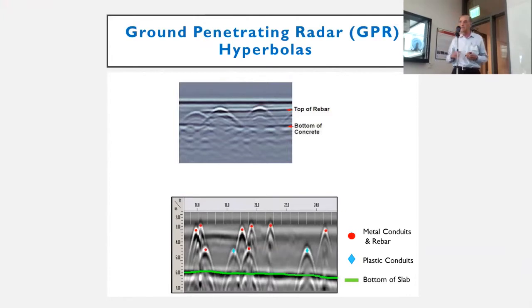So the way we do it is we push this cart along the surface. Let's say it's a concrete slab, and we'll pick up these hyperbolas. And these hyperbolas, when we pick them up, we mark them up on the slab or on the wall, and that tells us where the rebar or the post-tensioning or the conduit is. So it's very simple, but I want to warn you that it is something that is operator sensitive. Not everybody should be using this without going through a class on this. So that is at the top.